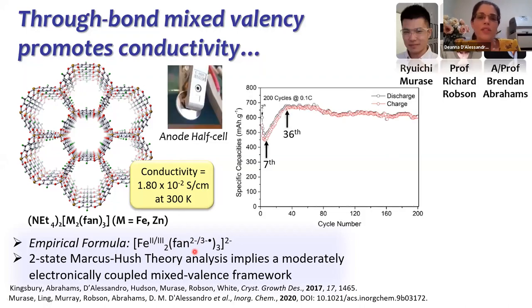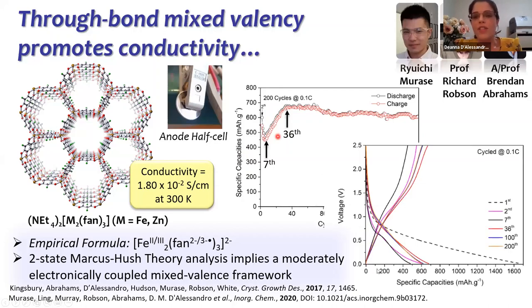And here we've been quite interested in the potential for battery applications. Here is the example of using this material in an anode half cell, and we've found a relatively high specific capacity for this material. Interestingly, there is an induction period as we cycle the anode half cell. If we look at the voltage as a function of time and of specific capacity, you'll note there's relatively little variation over many, many cycles. So we're now moving down the pathway of looking at the applications of these types of electroactive and semiconducting framework materials.